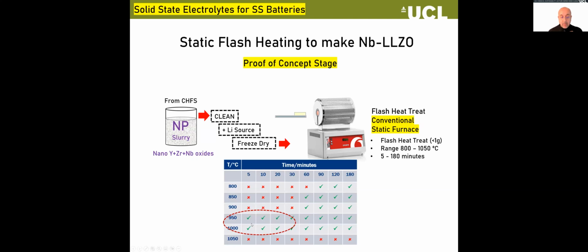Now, the critical thing for us is if we're going to scale this from a static furnace to a tube furnace, we ideally are only looking at a reaction time of 5 to 10 minutes. You can't really keep it in there much longer because it's a tube at an angle and the powder's kind of rolling down. So we were really looking for something that could be done in about 5 minutes. The other thing I'm going to add is that this powder is sitting in a crucible and the crucible is not preheated. So once it goes in there, it starts to get warm, but it's not preheated in any way.